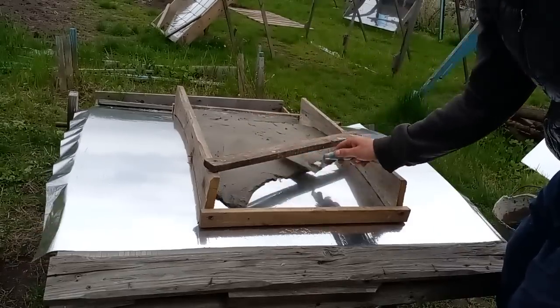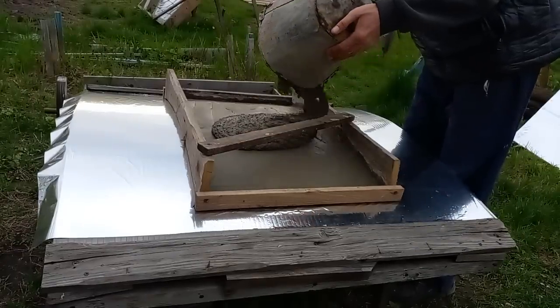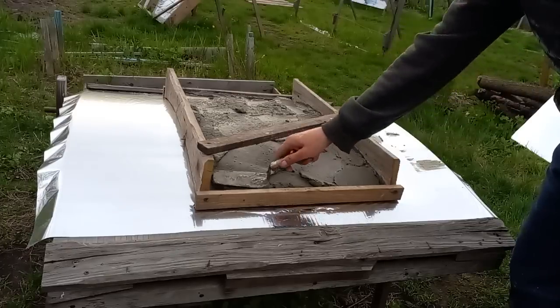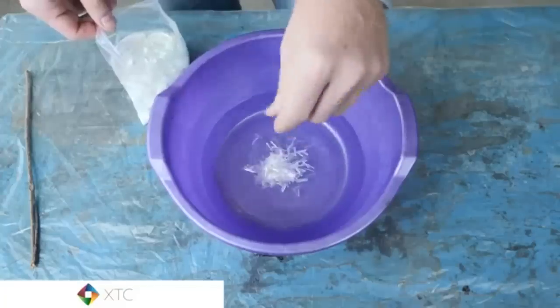After a short wait of about 1 hour, I put the second layer of concrete from sand and gravel. The second concrete layer must be reinforced, and I did the reinforcement not with steel rods, but with this polymer fiber.